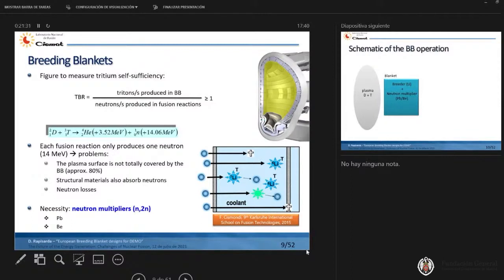Second point, the structural materials also absorb neutrons. These neutrons will go directly to the steel, and the steel will heat up, and we lose these neutrons. And the third point is that we have neutrons with high energy, and these neutrons can pass through the blanket without any interaction with the lithium. So at the end, we never will reach the self-sufficiency only with the lithium. And for that reason, we need in the blanket what we call neutron multipliers, which simply is an element which can absorb neutrons and produce additional neutrons. And in our case, we use lead and beryllium.